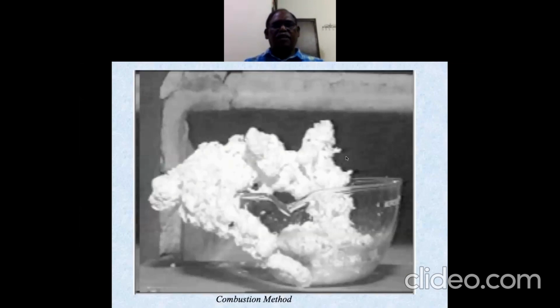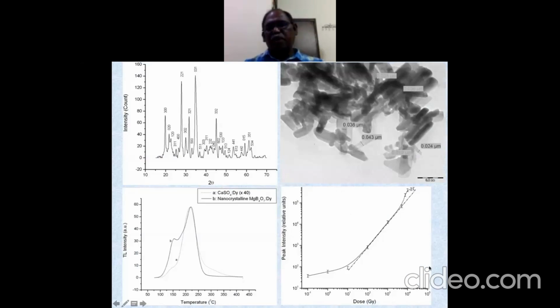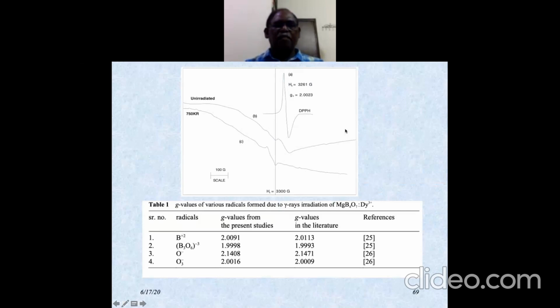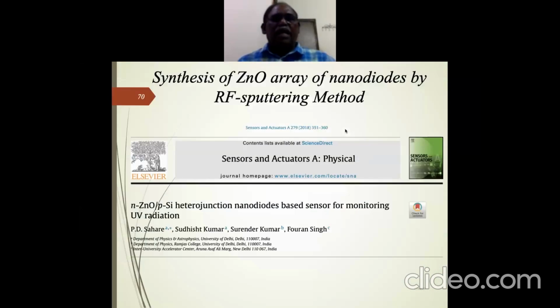And in this method, you can see that it is a very simple method. You take your material and some oxidizer, some fuel kind of thing, and you just burn. The advantage of this method is you can synthesize the material in 5 to 10 minutes. And again, you can see that in nanomaterial, you can measure even 10⁴ gray, and the sensitivity and other things are comparable. And you can also see these nanoparticles. We also have studied some defects over here by the ESR method. And in my last part, now I will talk a little bit on films.